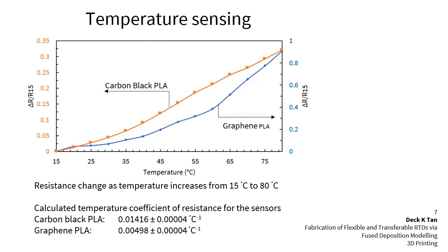Next, to measure the temperature sensing ability of the 3D printed sensors, the sensors were placed on a hot plate where the temperature was increased from 15 degrees Celsius to 80 degrees Celsius with a 5 degrees Celsius increment at every measuring point, and the resistance of the 3D printed RTDs was measured. The results are shown here, and the 3D printed sensors showed a positive temperature coefficient, and the sensitivity of the temperature sensors was measured and shown here using the temperature coefficient of resistance for the sensors.